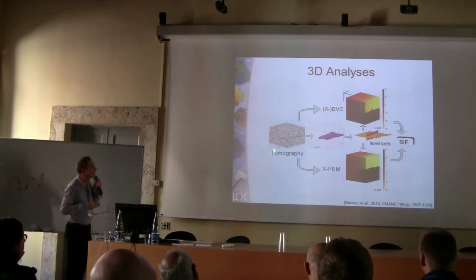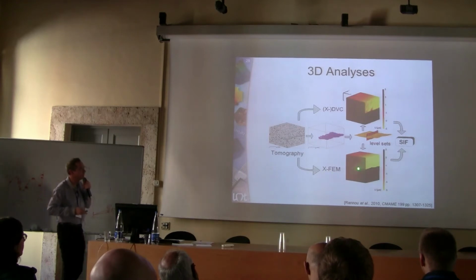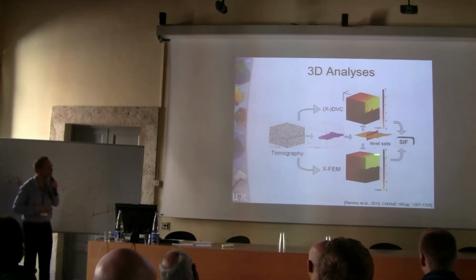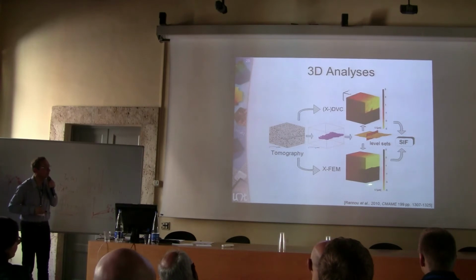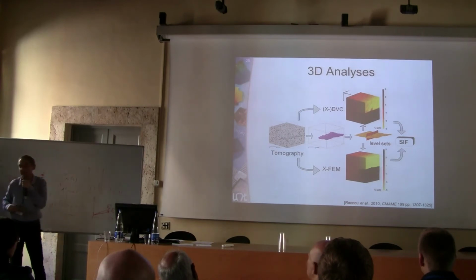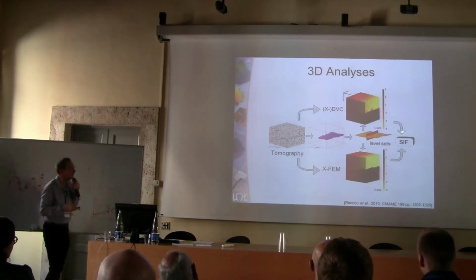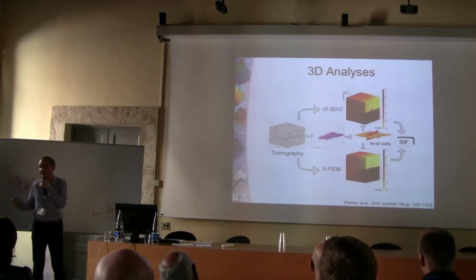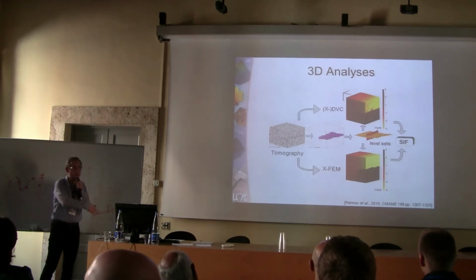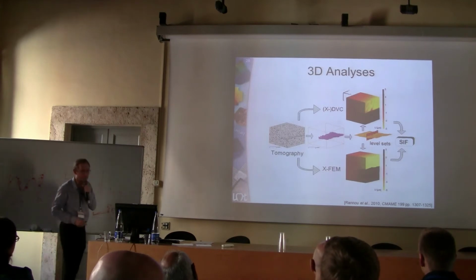But you can also, in parallel, run an XFEM calculation in which you prescribe the measured boundary conditions on the top and bottom part of this volume. And then compare the stress intensity profiles you measure experimentally and predict numerically.